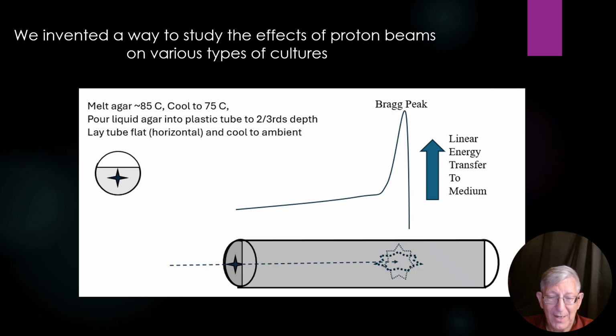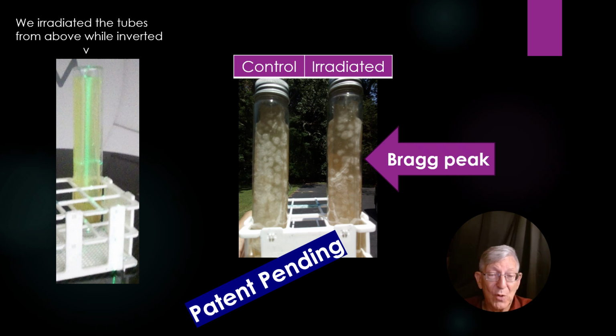Bam. And from all the arguments I've told you, we would expect a progressively more effective anti-microbe effect along this as we approach the Bragg peak. And then at the Bragg peak, we would expect a pretty dramatic effect. And then, interestingly, beyond the Bragg peak, we wouldn't expect to have any effect. And so we did this, and boom, here's what we got.